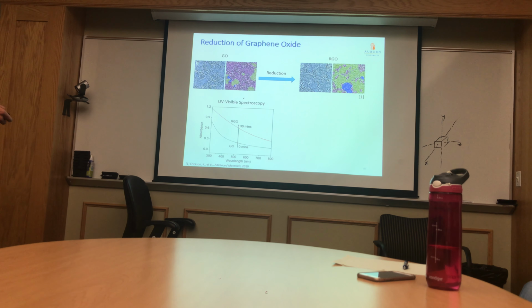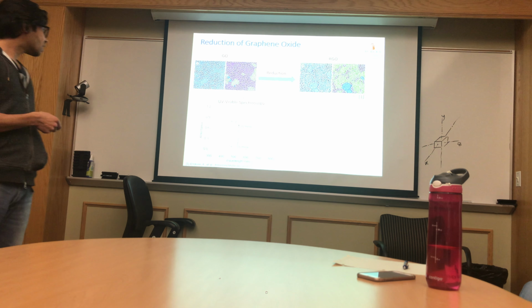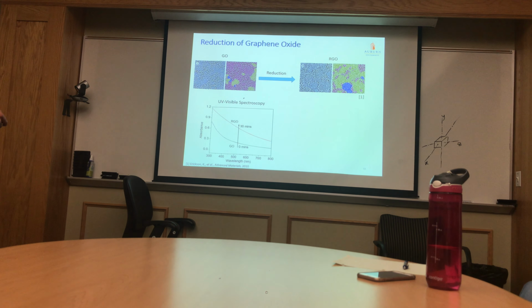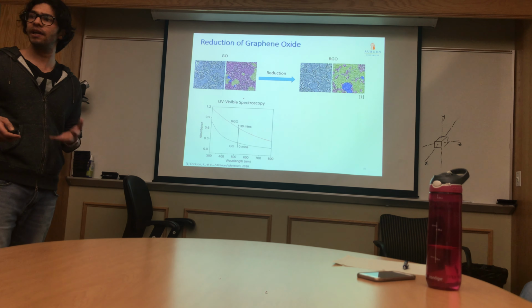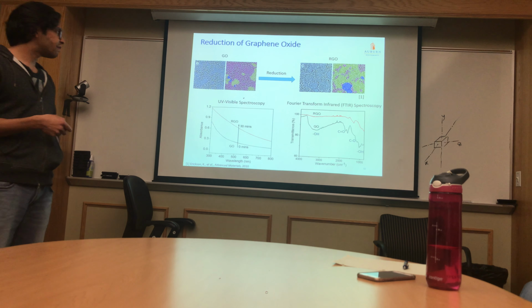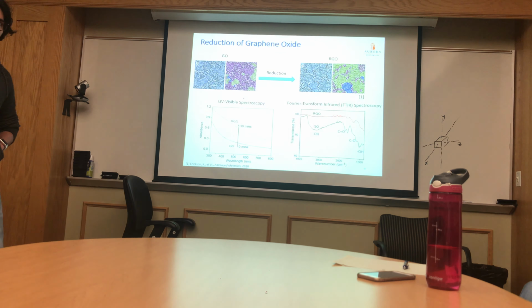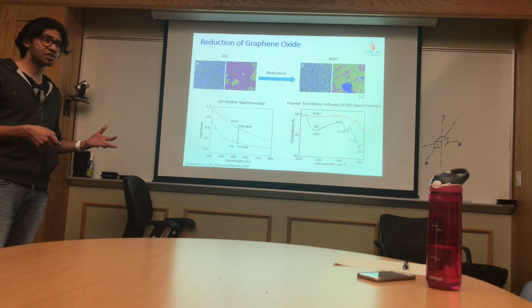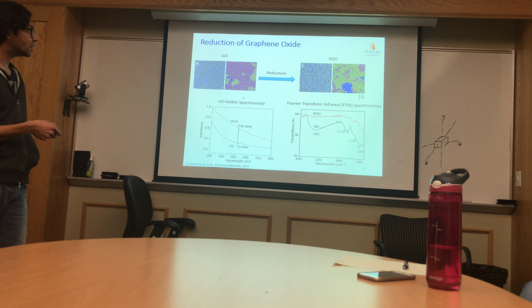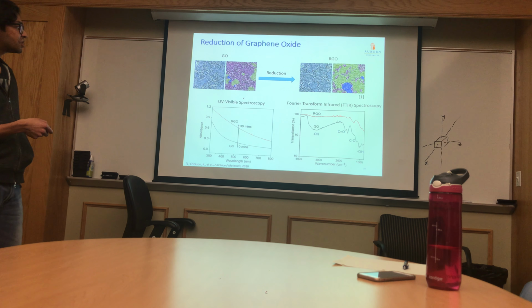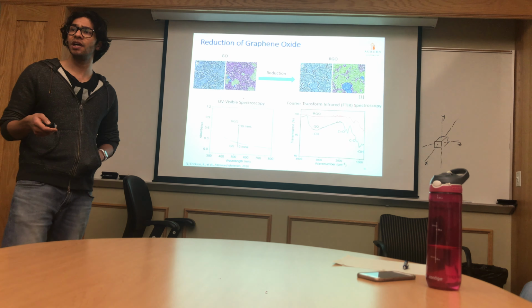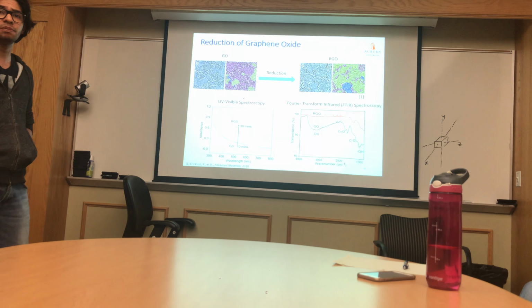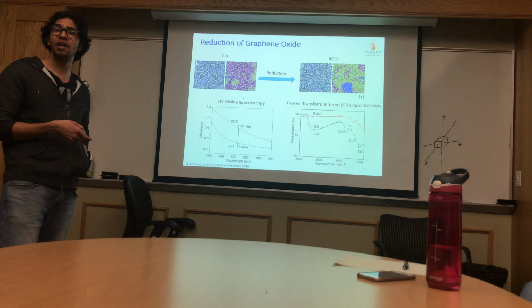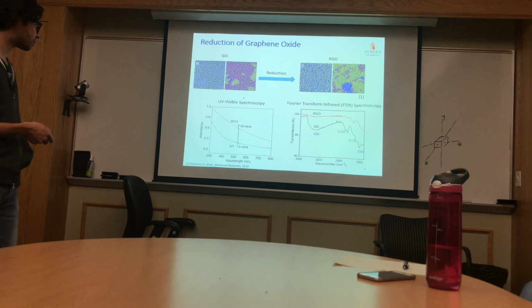Now, we performed UV-visible spectroscopy on graphene oxide and reduced graphene oxide after photoreduction, and we realize that the absorbance has increased, and this is actually the characteristic of graphene oxide and reduced graphene oxide. Further, Fourier transform infrared spectroscopy was performed, and here we see that the results actually agree with the literature. Here we see that graphene oxide has a very large OH vibration peak, which completely diminishes in RGO. It suggests that most of the hydroxyl functional groups have been reduced during the photoreduction, which is plausible because most of the basal plane of graphene oxide has been filled with hydroxyl functional groups.